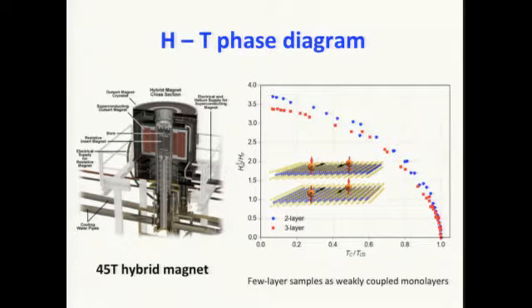So that's the data from about a year ago. After we published our results, we got access to the 45 Tesla hybrid magnets, and we can now map out the full phase diagrams, at least for the bilayer and the trilayer material. This is shown here, the dots. You can see that both of them exhibit this square root dependence at the beginning, and then go way beyond this Pauli paramagnetic limit here. My argument, as Philip mentioned, only holds for a monolayer material, but the bilayer and trilayer material also go way beyond the Pauli paramagnetic limit.